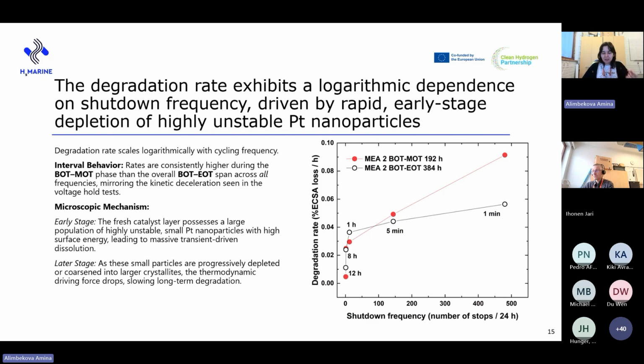When we again quantify the degradation rates versus the shutdown frequency or number of stops per 24 hours, so at 1 minute the shutdowns are more frequent, we can see first that at higher shutdown frequencies, the beginning of test to middle of test degradation rates are higher than the beginning to end of test.